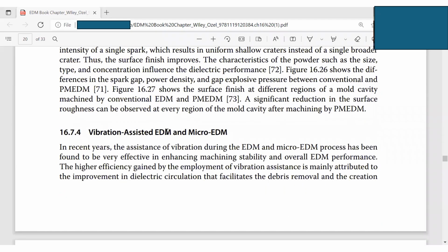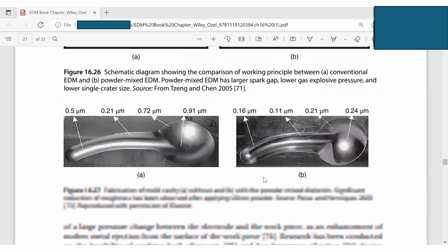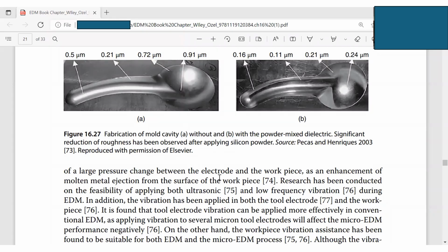Next one is vibration-assisted EDM and also micro EDM. EDM and micro EDM are just different scales. So in recent years, the assistance of vibration during the EDM and micro EDM process has been found to be very effective in enhancing machining stability and overall EDM performance. The higher efficiency gained by vibration assistance is mainly attributed to the improvement in dielectric circulation that facilitates debris removal and the creation of a large pressure change between the electrode and the workpiece, as well as the enhancement of molten metal ejection from the surface of the workpiece.